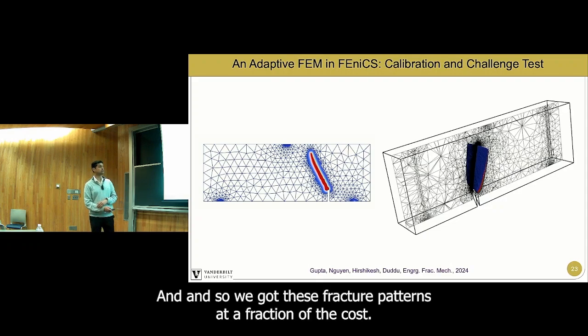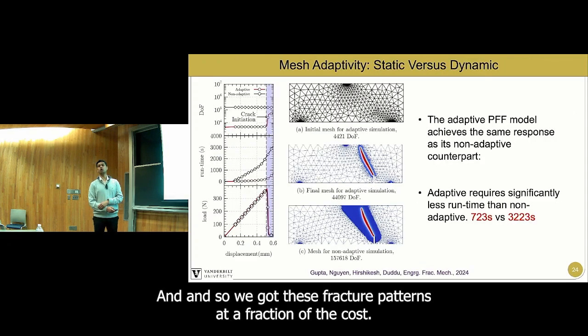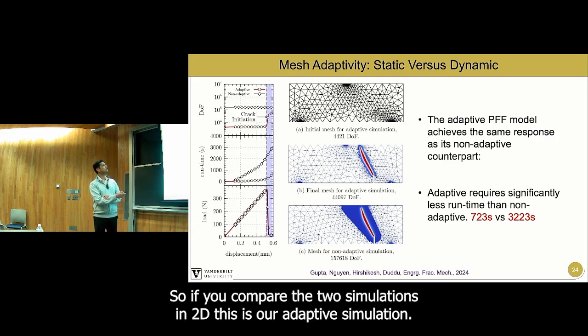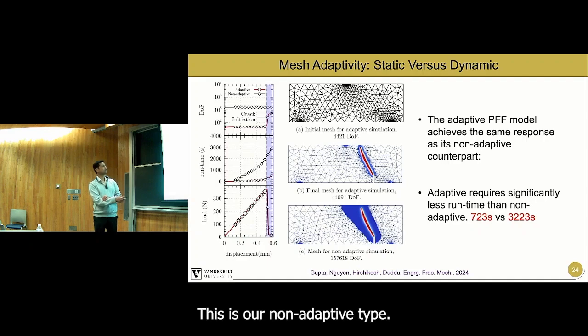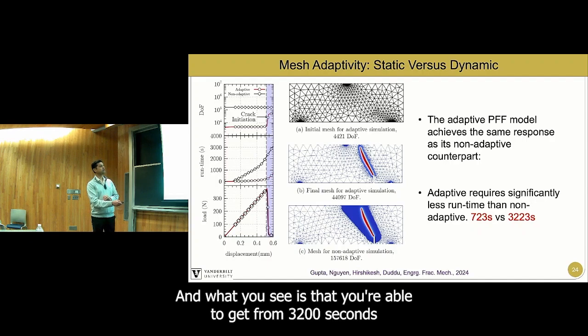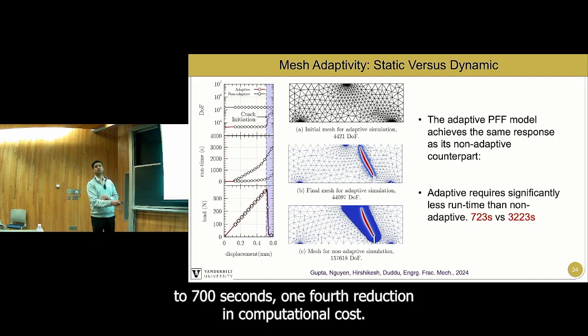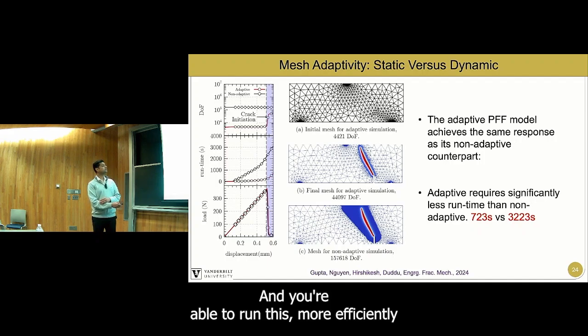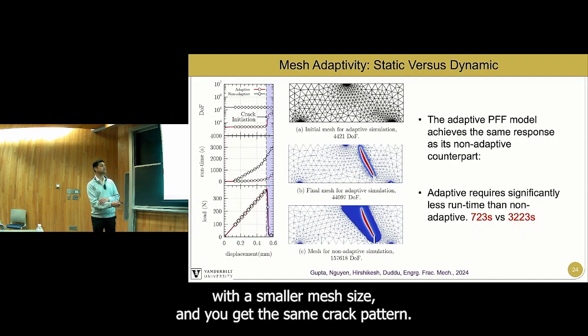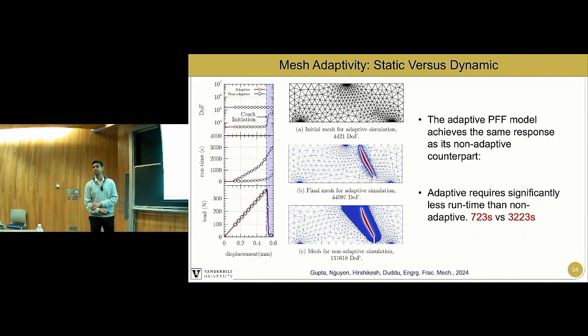And so we got these fracture patterns at a fraction of the cost. If you compare the 2 simulations in 2D, this is our adaptive simulation. This is our non-adaptive type, where you manually refine it as standard. And what you see is that you're able to go from 3,200 seconds to 700 seconds, about a 1/4 of the computational cost. And you're able to run this more efficiently with a smaller mesh size, and you get the same crack pattern.